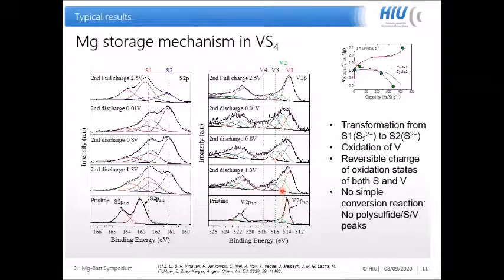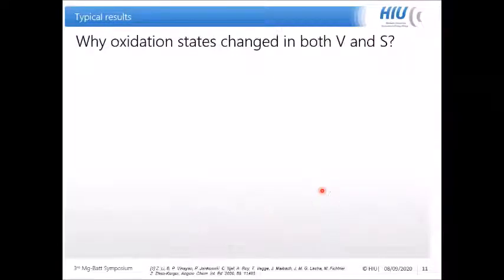And other than that, we didn't find any peaks related to long chain polysulfide, elemental sulfur, or metallic vanadium, which means we don't have a conversion reaction taking place during the process. So the question is: why do we have the oxidation state change in both vanadium and sulfur, and even the vanadium has been oxidized during magnesium insertion?